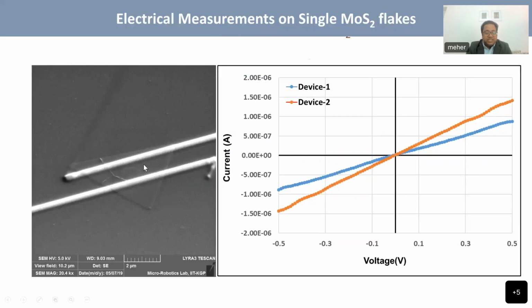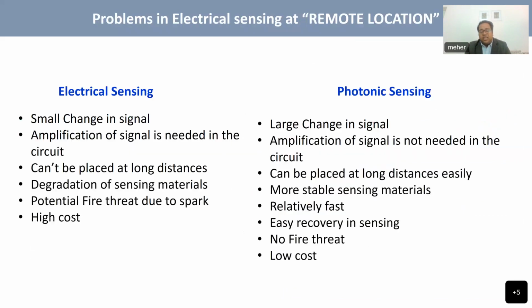And this is the single nanoflake. You can see here the flake is around 4 micron. And these are the platinum electrodes. With the help of these very miniaturized electrodes, we could measure the resistance of this flake. But if we talk about the sensing of different gases, the absorption was too small, so we were not able to detect the signal.